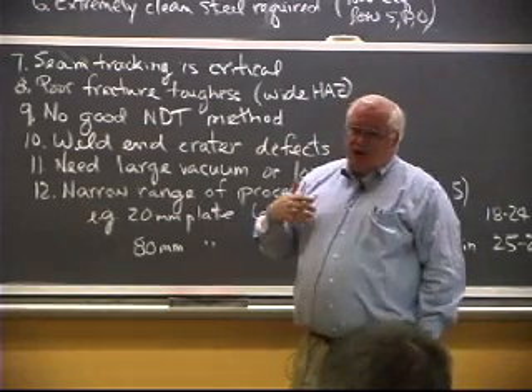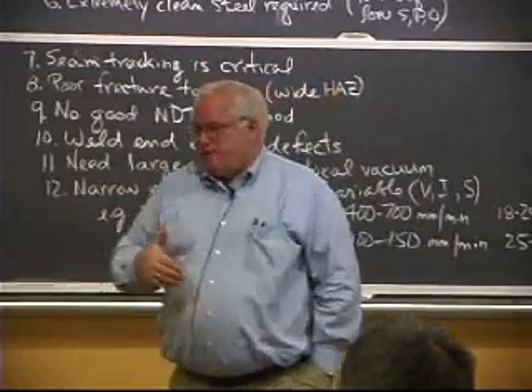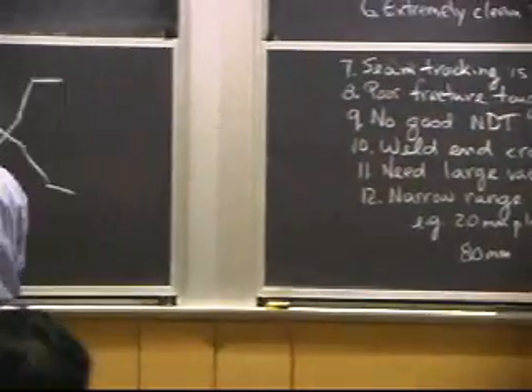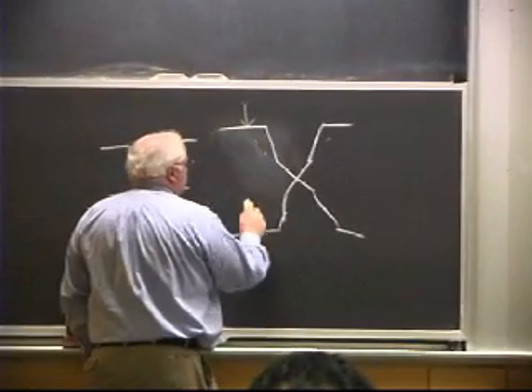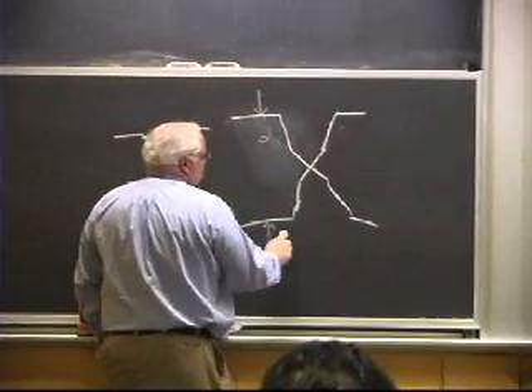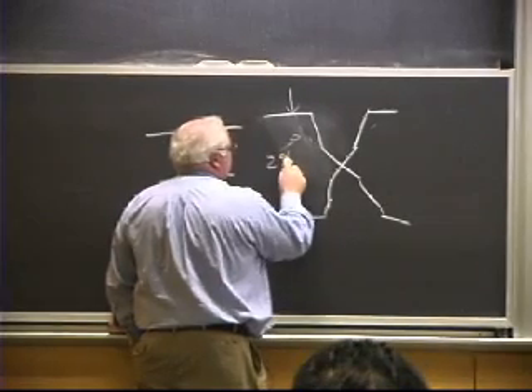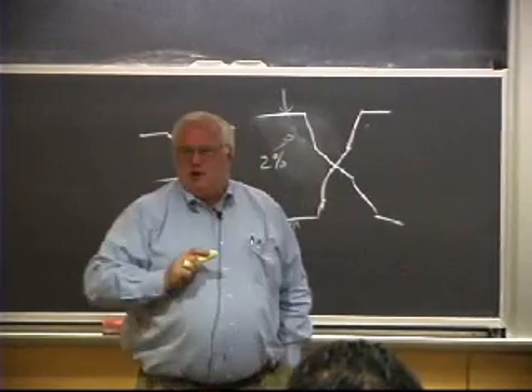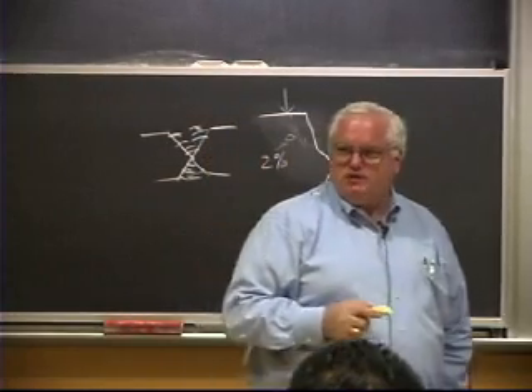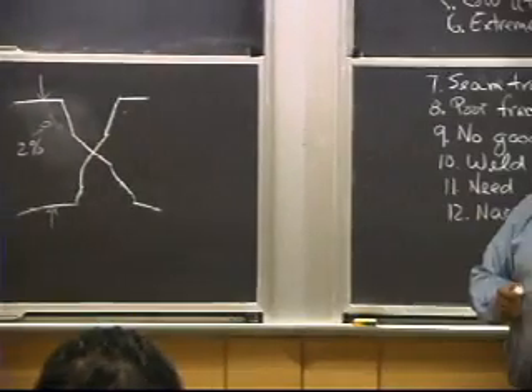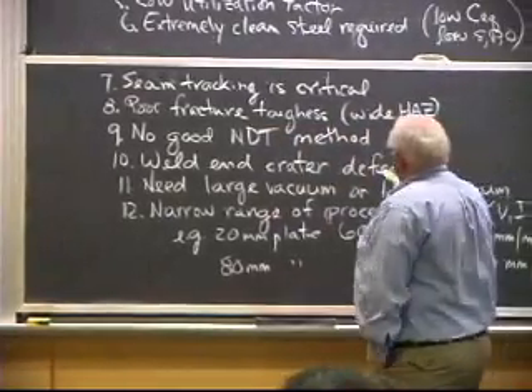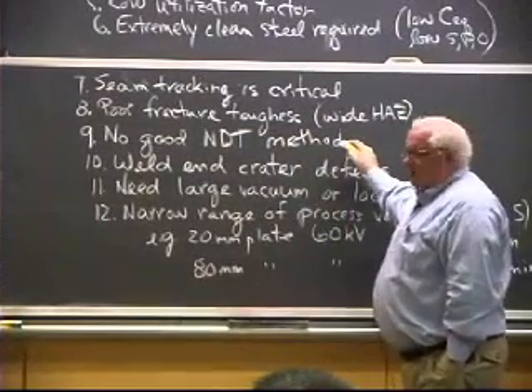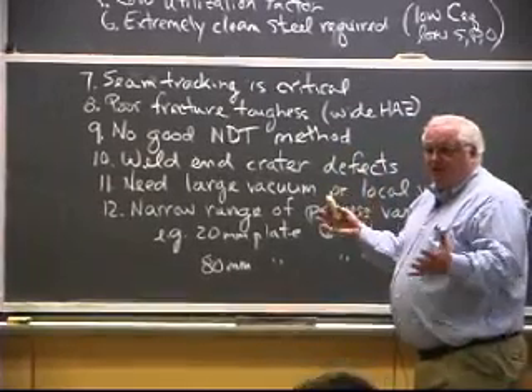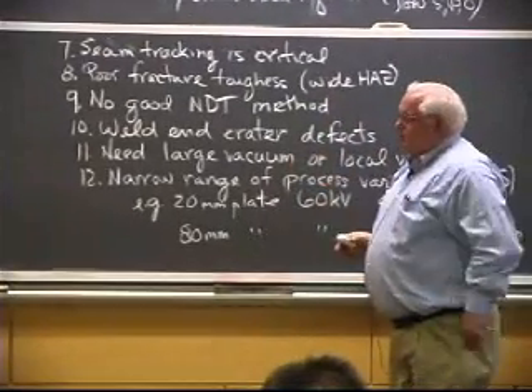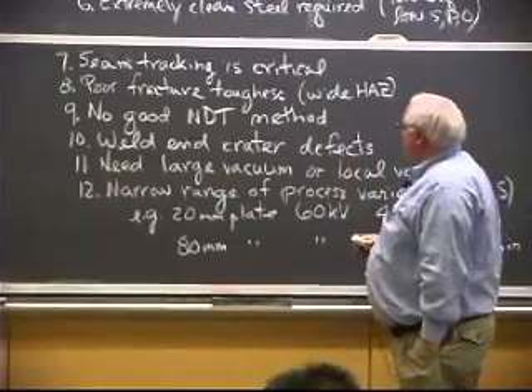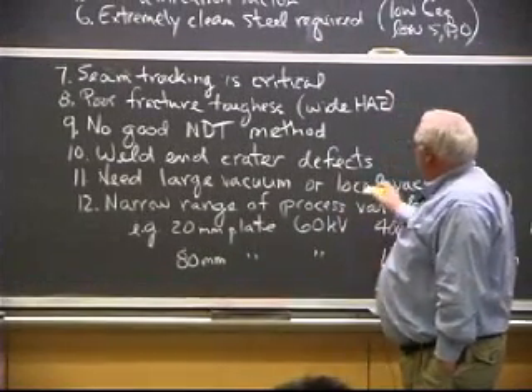No adequate non-destructive test technique for something that thick. Typically on an X-ray inspection, and this is part of the rest of the course, something about 2% of the thickness would show up on the X-ray if you're looking really carefully. Well, when you're talking 8 inches thick, something that's 2% of the thickness gets to be pretty substantial. Okay, you can do ultrasonics and stuff, but it doesn't matter what technique you use. Because you're looking at something big, your sensitivity is going to be some fraction of the thickness, and therefore you've got larger flaws than you'd like to deal with in terms of fracture toughness.